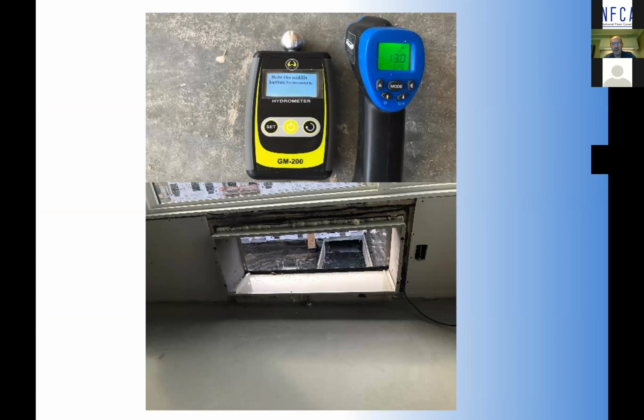We've got these AC vents sticking open, and water leakage and ingress getting in through them. You've got single-digit temperatures in those particular rooms. You've got a new pour that's got moisture still in it that's trying to evaporate at these cooler temperatures. So site conditions are still a major challenge. It doesn't matter if it's a concrete pour or a gypsum pour, the same thing holds true. We have to have proper site conditions before we install floors.